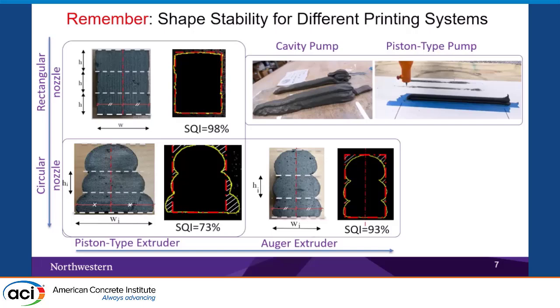We got to the point that we cannot simply say that we have a printable mix. This printable mix must be related to a specific printing system. When we changed the nozzle shape from rectangular to circular, we got different shape stability. When we changed the extrusion system from a piston type system to an auger system, we got different printing shape stability. So when we say that we have a printable mix, we need to relate this to a specific printing system.